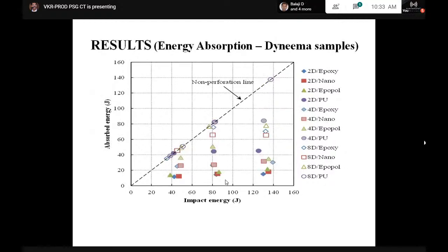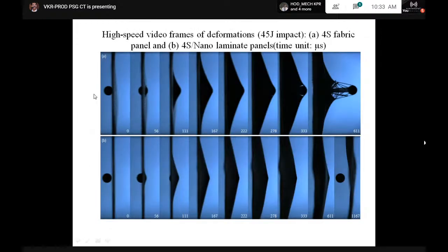That is one thing. Then about the polymer, we have some results to share, and this is the impact behavior of the steel projectile into the composite. You can see the number of frames per second. This is the impact, then it tries to deform, then the deformation, and finally it breaks out. In a 4S fabric panel it breaks out and comes through, and at the bottom you have the 4S/Nano laminate panel, which deforms the laminate and doesn't allow the steel ball to pass through. It actually stops it.